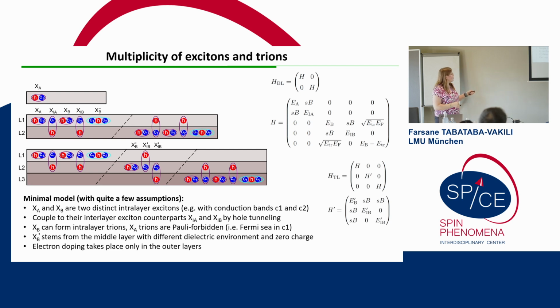And then in the trilayer, we believe that this XB prime stems exclusively from the middle layer, and that the energy shift comes from the different dielectric environment, and the factor 2 in curvature stems from XB prime being able to couple to two interlayer excitons. And then, curiously, we do not observe any signature of an XA prime, so it seems like we don't have any signature of the C1 conduction band, which could be because it shifts to higher energy, the band structure changes, or something else. If you have any ideas, please let me know.